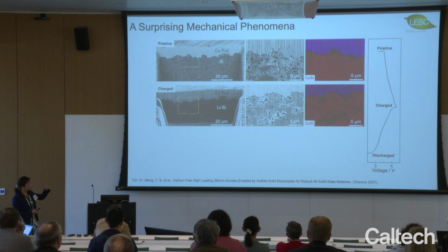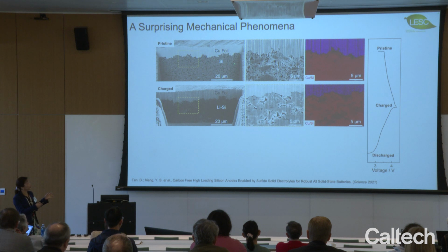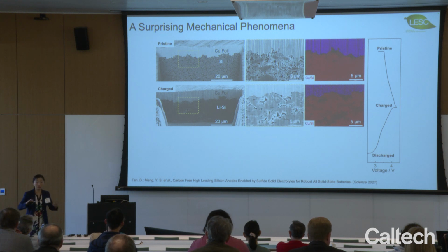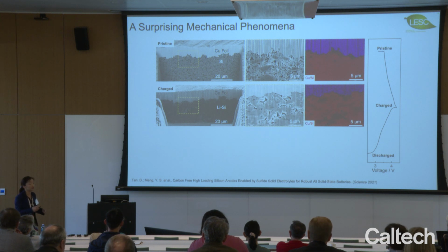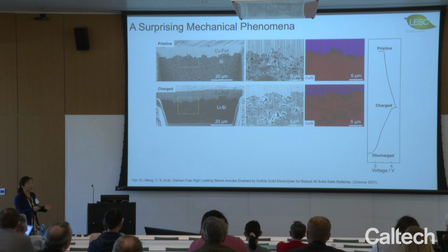And when you do the process and lithiate this, in fact, it is almost completely pore filling. And when we shine the X-ray on this silicon, it's beautiful silicon crystals. At the end of the charge, it is completely amorphous. There's not a single crystalline signal. So this is also one of the reasons it is difficult to understand what we made. A lot of people are using the pair distribution function, a total scattering method, to understand the structure of lithium silicon.